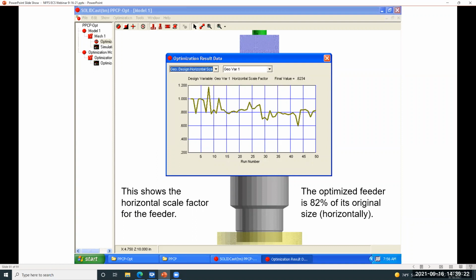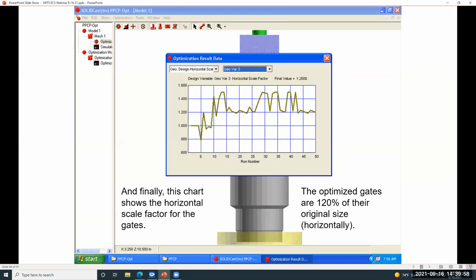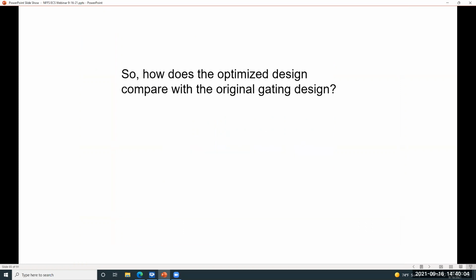This shows how the feeder bar changed in size. It was originally at a value of 1. It dropped down to 82% of its original size. And for the feeder bar, the height dropped to 83%, so about the same each way. The pouring cup, the size of that dropped down to about 42% of its original size, so that decreased quite a bit. And the gate actually got a little bit bigger, and that was in order to promote directional solidification.